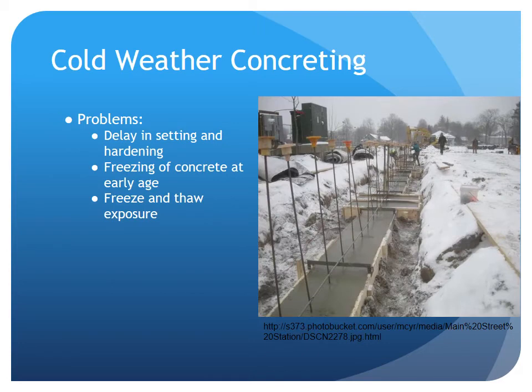The pouring of concrete in cold temperatures greatly increases the setting time, which can lead to decreased strength in the concrete. If the water in the concrete mix completely freezes, the hydration of cement may stop completely. Even if there is only partial freezing and thawing, the concrete will be negatively affected.